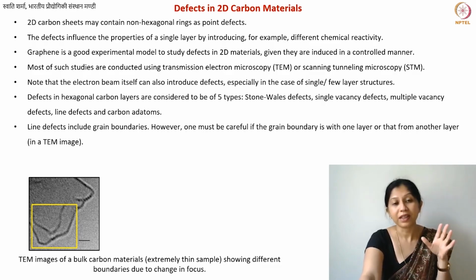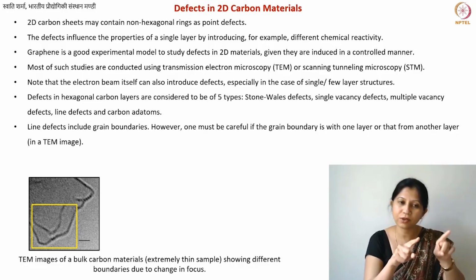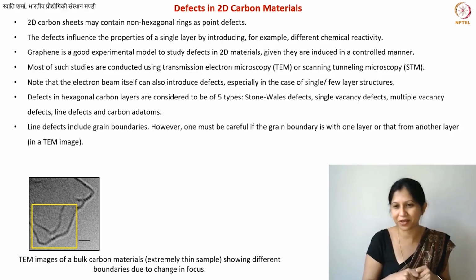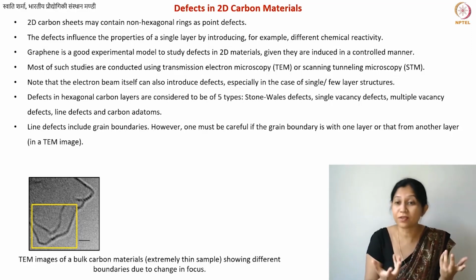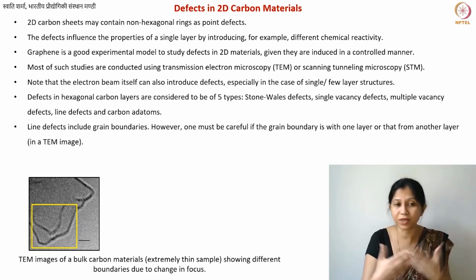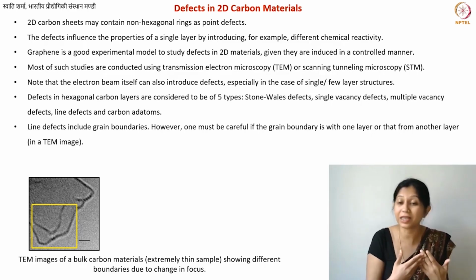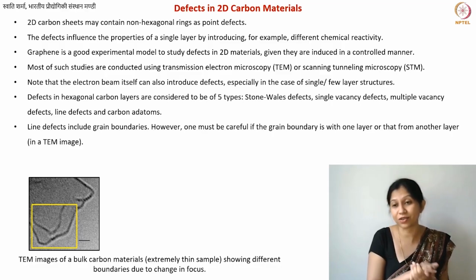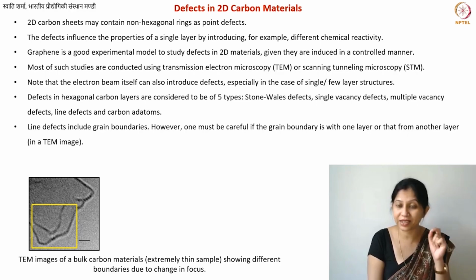Okay, so you see this yellow box I have drawn here. This is the point where you could say that this is a grain boundary, or some sort of dislocation, and you may try to analyze it, but there is also a possibility that these are 2 layers stacked on top of each other, because all you see in the case of TEM images of graphene is the edges. This is also very important: one problem is the lack of depth perception, but also the fact that you see only edges.